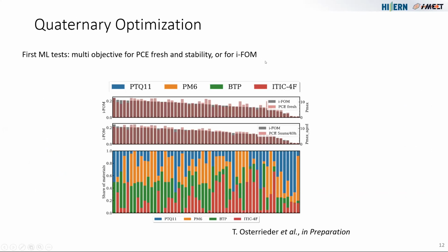So this industrial figure of merit, it includes the performance, the stability, and the price. And basically what we can see is that with some of the more expensive materials like PM6, we can get systems that perform equally well when considering the price, the whole IFOM. For example, with PTQ11, which is a little less efficient and a little less stable, but it's much cheaper. So in terms of figure of merit, this material also can perform pretty well for a potential product.